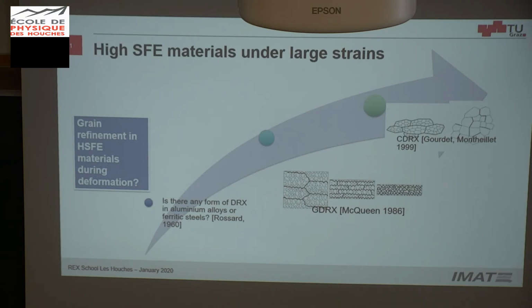And here the idea is that the subgrains are formed, and these subgrains are also allowed to rotate. The dislocation increment is going into the low angle grain boundaries, so the misorientation between subgrains increases until you have the formation of high angle grain boundaries. So it's a very simplified interpretation of both.